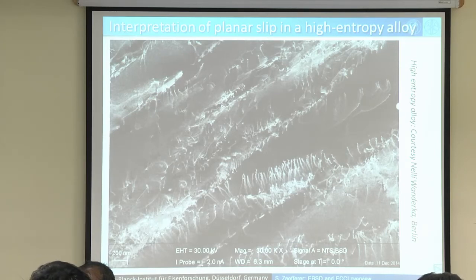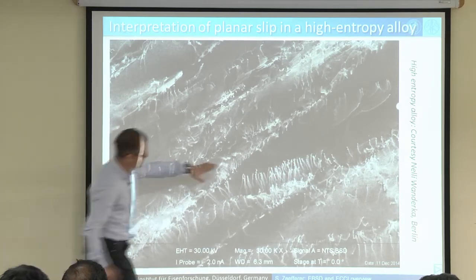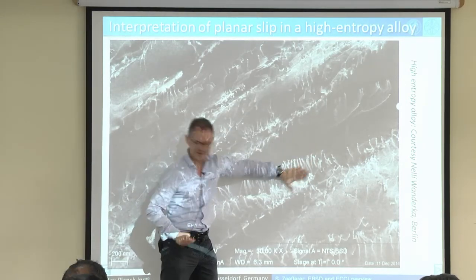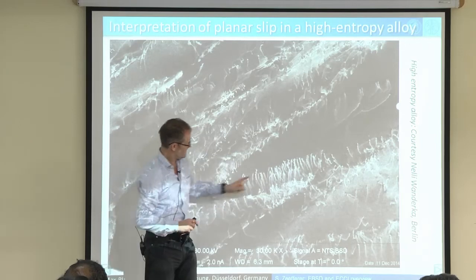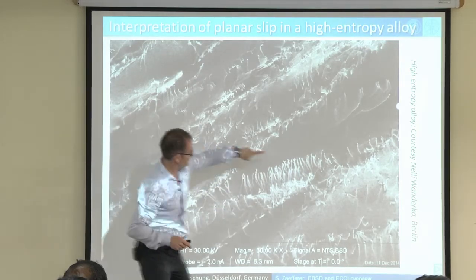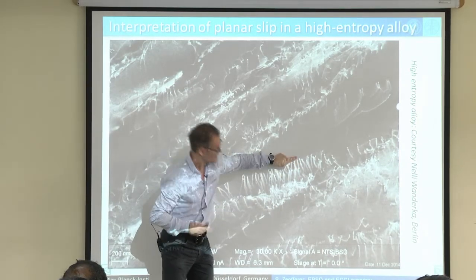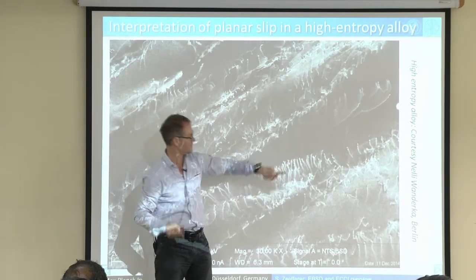So first, if I would not tell you this is an ECCI image, you could also guess this is probably a TEM image. What you see here are all the dislocations. They are gliding on different slip planes, obviously very dense planar slip. And if you look, for example, at these dislocations, this one here is a typical example, they show this funny oscillation contrast.